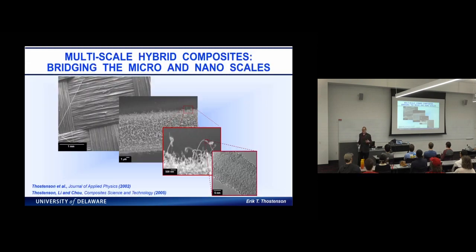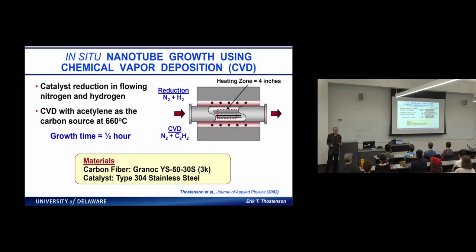And again, I showed this slide before, but I think the key challenge and the opportunity is that we can combine the reinforcement scales together. When I first did this, we were using chemical vapor deposition, a very high temperature process, over 600 degrees C. So very few fibers are going to survive that process. You really need either a ceramic, or even some carbon fibers will start to degrade. But I was intrigued by this.